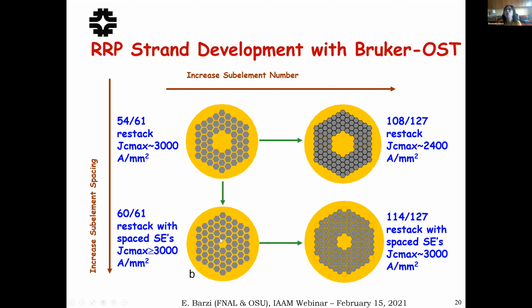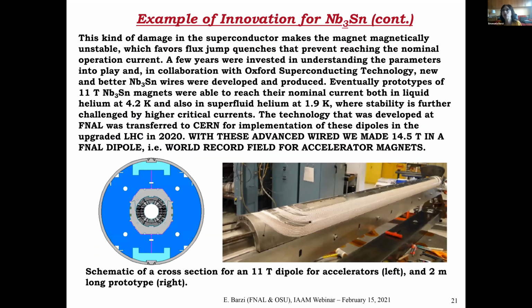Because actually, you know, this merging happens not as much during the heat treatment itself, when everything diffuses, but, contrary to intuition, for me at least, I thought it would happen in the heat treatment stage where you have thin diffusion and everything may get glued together. But actually we found out it happened during the plastic deformation in cable fabrication. So we asked industry to separate the subelements, and if you can believe it, once they were separated, even when subject to such high plastic strain, they would not merge as much. And that's how we solved the big problem of the magnetic instabilities at low fields in this magnet,